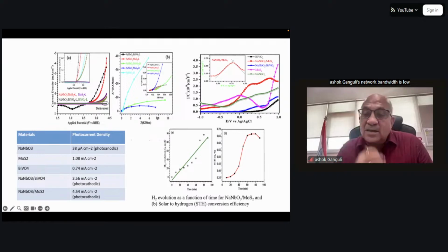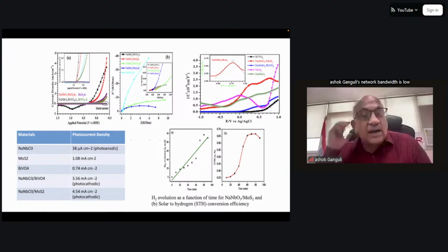You can also measure other properties like the hydrogen evolution. You can show the hydrogen evolution as a function of time. You can measure what are called Mott-Schottky plots, and from the shape of the plot, you can tell the nature of the charge carriers. So if you have a positive slope, it indicates negative charge carriers, and a negative slope indicates positive charge carriers. So a Mott-Schottky plot is a plot of 1 by capacitance squared with the applied voltage. And you can see that here both the slopes are present, which tells you both types of charge carriers are there. That means in your heterostructure, you have one N-type and one P-type charge carriers, and that is reflected in your Mott-Schottky plots. Okay, so you have sodium niobate as one kind, right? And molybdenum sulfide is another kind.